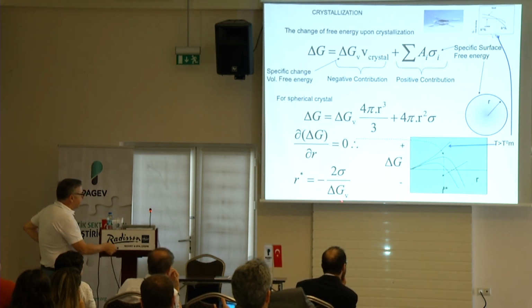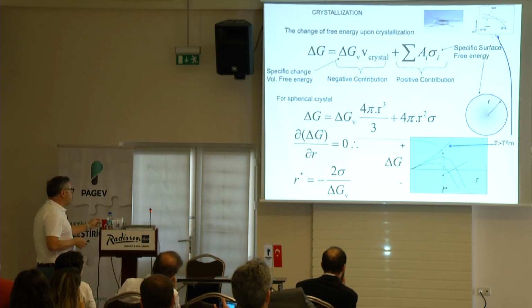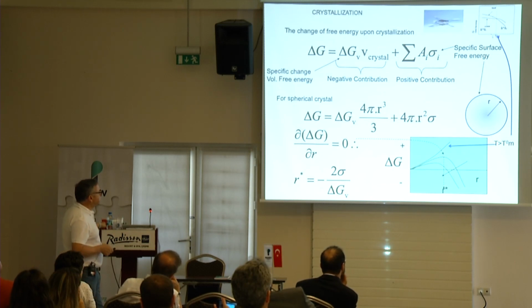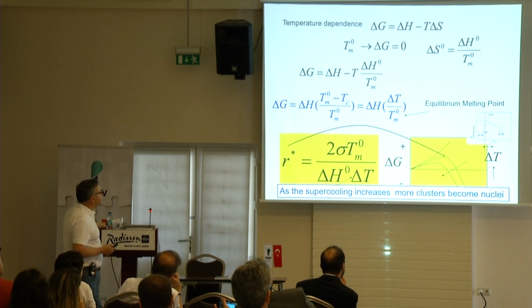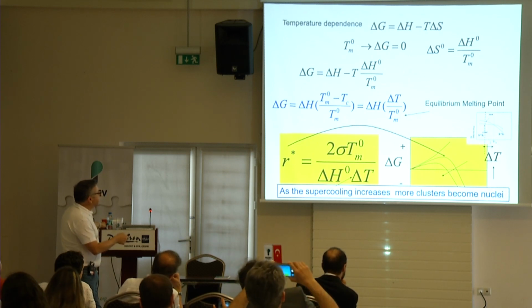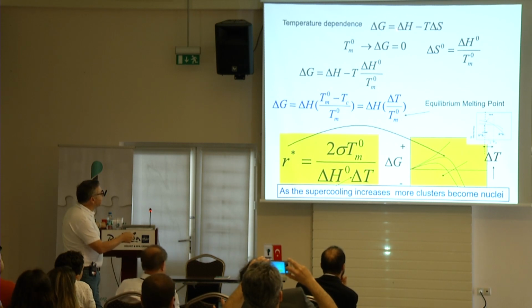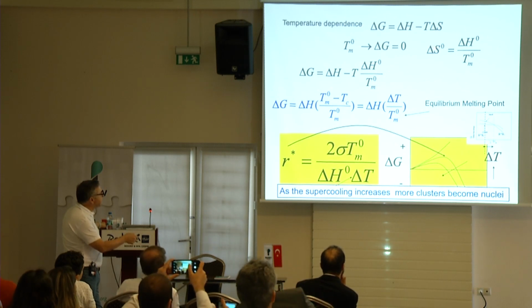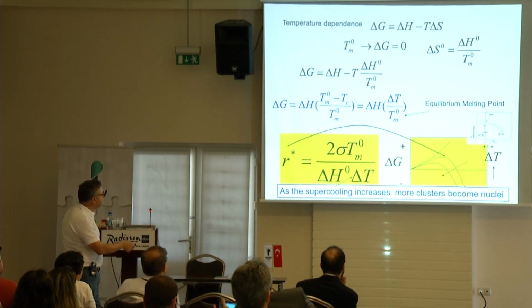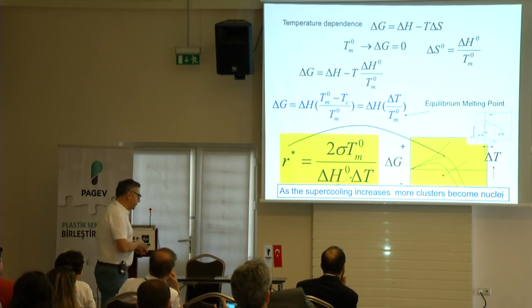The reason why you have a negative is because this has a negative value, because of the negative nature of how we measure it. Simple as that. So at the equilibrium melting temperature, the free energy is equal to 0. This is the classical thermodynamic equation. At the equilibrium parameters, entropy is enthalpy divided by the equilibrium melting temperature. You plug all that in. This is a very powerful equation for critical nuclei size.